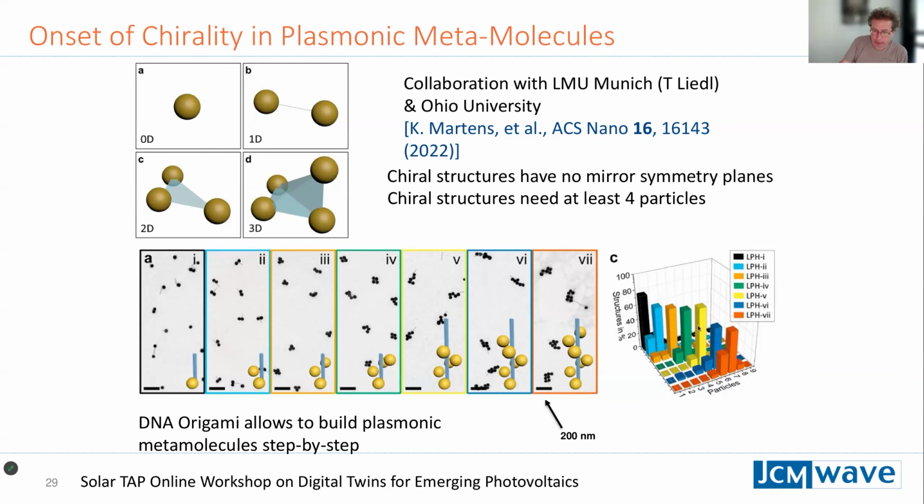And you see here you can build deterministically structures with 1, 2, 3, and so on nanospheres which wind up like a helix along this DNA origami here. The nice thing is you do that in a solution and you make millions or billions of these helices at the same time. So it's a very fast fabrication method.